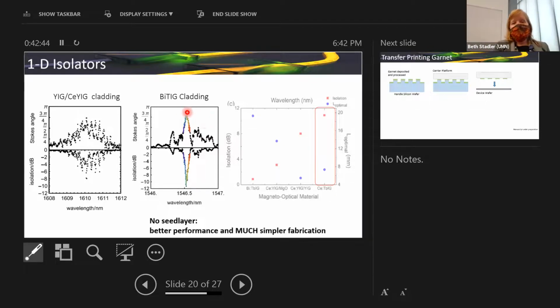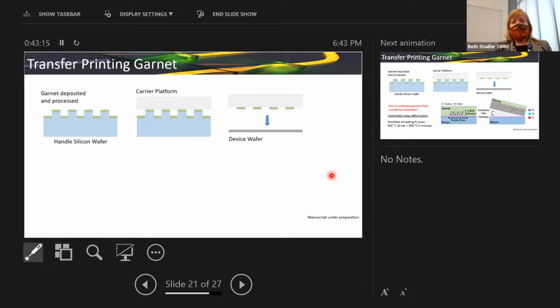And we see decent Faraday rotation, or a decent isolation. We'd like to get up to pi going forward and pi coming back to get an ideal isolator. But right now we end up getting 11 dB isolation. We made a device, the best device length is 7 millimeters, of silicon 500 nanometer core, which means the interaction with the cladding is not as much as with 220, but we still were able to get an isolator with that 500 nanometer core.